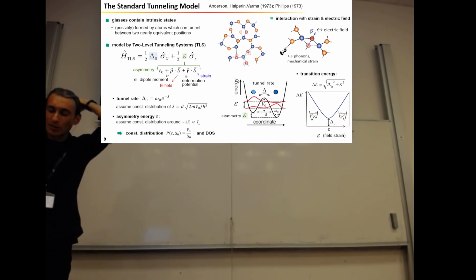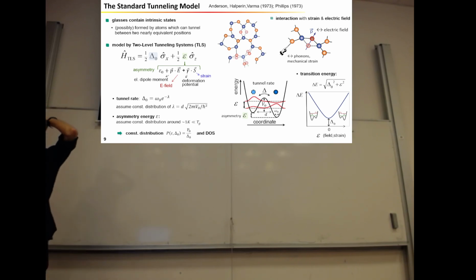And this is of course a very central prediction because this allows us to verify our measurements. We know, for example, in specific heat, we just need to know how many systems you can excite there as a function of temperature, and then you get basically this linear temperature dependence as I showed before.